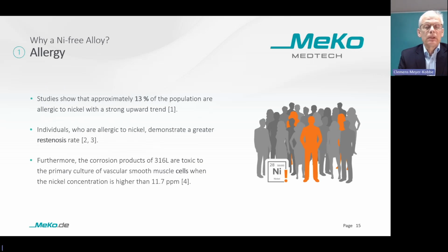So, the main question is, do we really need a nickel-free alloy? What are the constraints? In general, studies show that approximately 13% of the population are allergic to nickel, with a strong upward trend. The number of 13% varies a bit from study to study, but in general, more than 10% have a nickel allergy. Very often a light allergy, not very strong. It is known that women show a higher incidence of nickel allergy. It is assumed that they develop the nickel allergy due to their earrings, but also piercings.